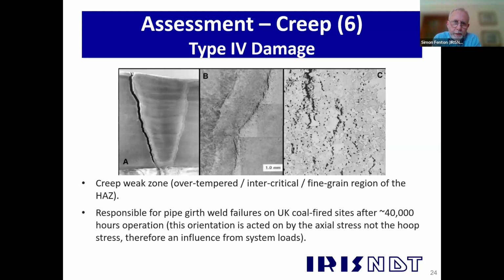So there's 3 photographs there, starting on the left with a full view of a weld with a full through thickness Type 4 crack running through that weld. Photograph B shows this at high magnification, and you can see the creep damage forming in that Type 4 region, this fine-grained region. And then in the photograph there, marked C, you can see the individual cavities and areas where the cavities are joined to form both orientated damage and also micro cracks. So that's Type 4 damage, and that's a real problem for the industry.